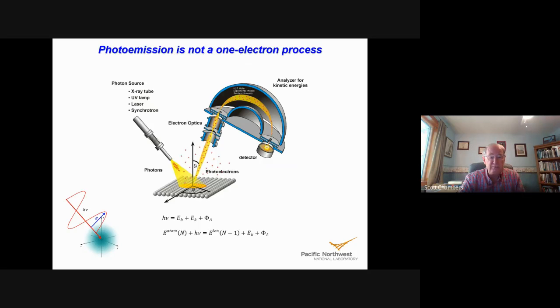We are far better off if we recognize that what the X-ray really does is it takes an n-electron atom and it transitions it to an n-1 electron ion and a photoelectron. And if you then combine those two equations, you end up with this formula for the binding energy. It's the energy difference between the n-1 electron ion that you have after core level photoemission and the n-electron atom that you had before. And the reason that this is really important is because the wave functions of those n-1 electrons in the core ionized species are quite different than the same orbital wave functions were for the atom prior to photoemission. So it's really very important, I think, that we understand that all of the electrons in the atom are involved at some level, and in some cases more than others, depending on the element.